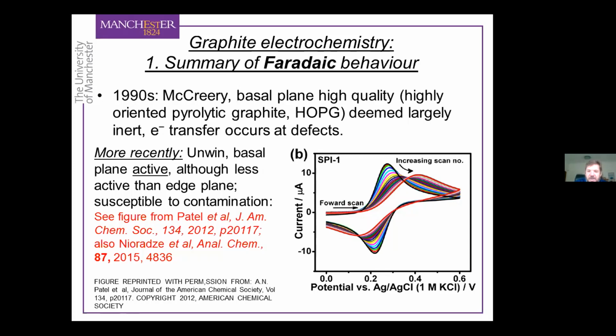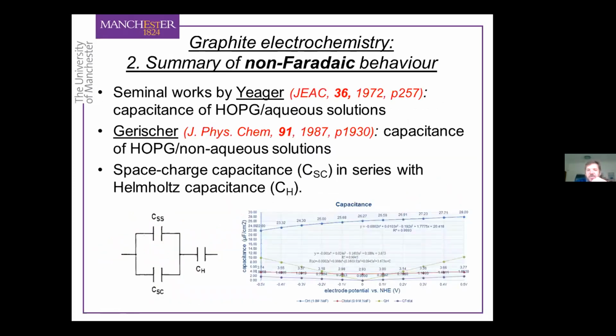So that's Faradaic electrochemistry. If we look at non-Faradaic electrochemistry of graphite, again, McCreery and Unwin are the two names that stand out in terms of Faradaic electrochemistry. I would say there's two names that stand out in terms of understanding the capacitive behavior of graphite surfaces. And that is the work of Yeager, going back to the 1970s, and Gerischer during the 1980s and early 90s, I think he worked in this area. So Yeager looked at the capacitance of graphite in aqueous solutions and found that it was low. It was much lower than you see for metal surfaces. And he rationalized this qualitatively, but a more quantitative analysis had to wait for Gerischer's work, because Gerischer, of course, was an expert in semiconductor electrochemistry.